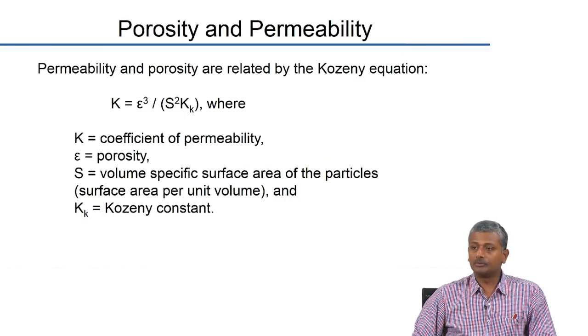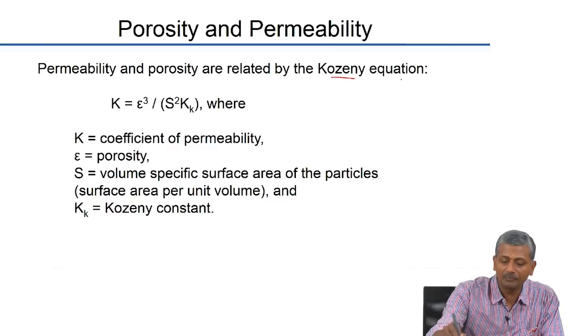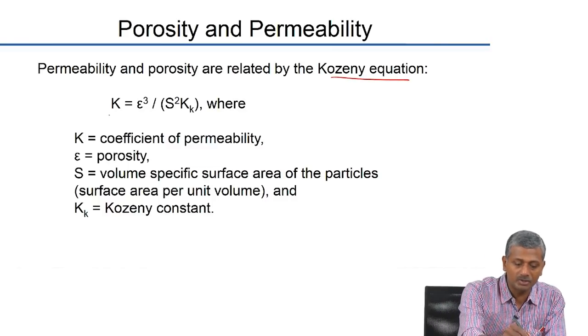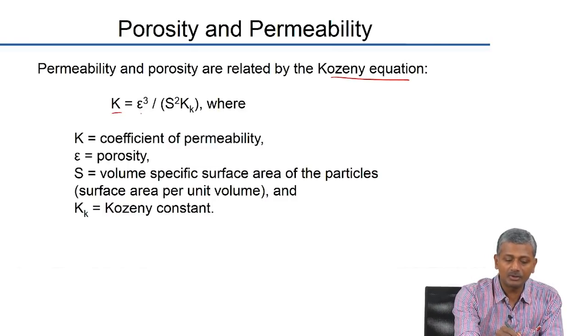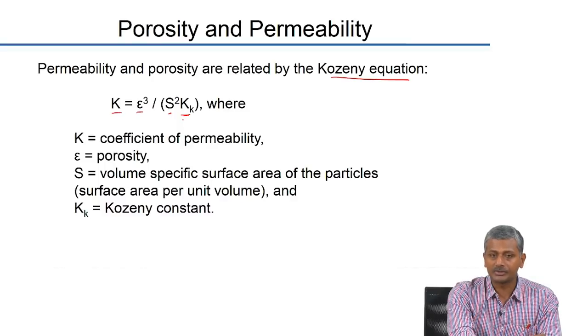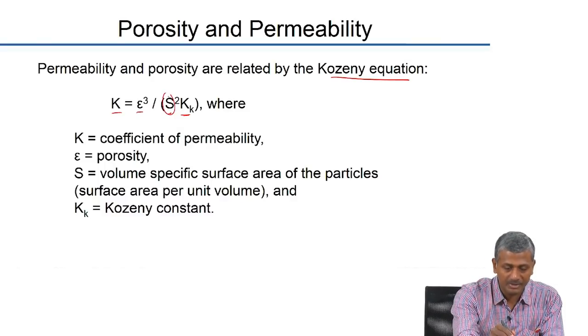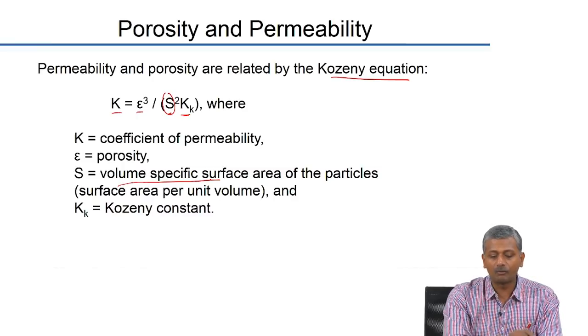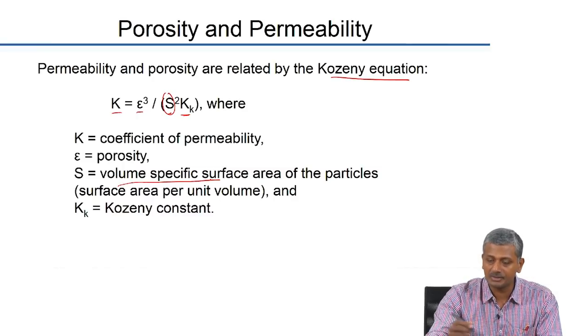Now, people have always tried to explore this relationship between porosity and permeability. For general porous materials, the porosity and permeability can be connected with what is known as the Kozeny equation. According to this equation, the coefficient of permeability K is equal to the cube of porosity divided by square of surface area multiplied by a constant called the Kozeny constant. Now let us look at what this Kozeny constant is made up of, but meanwhile I should tell you that S, surface area, is the volume specific surface area of the particles. That means